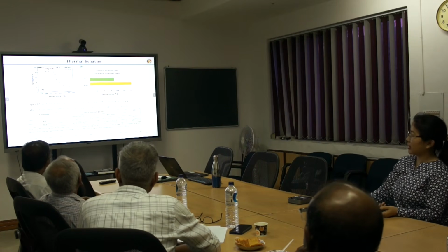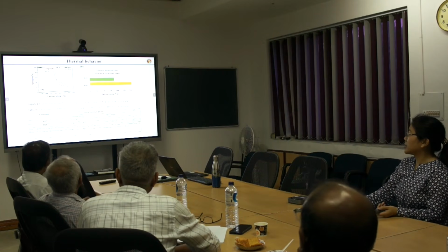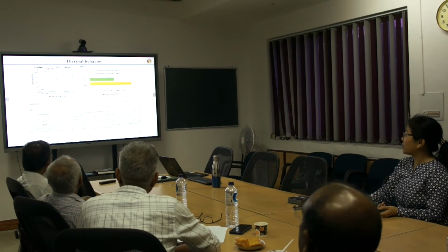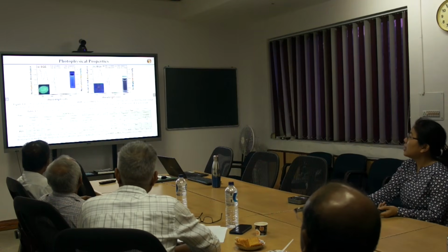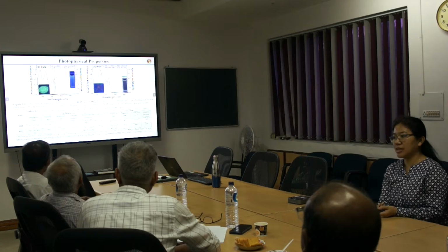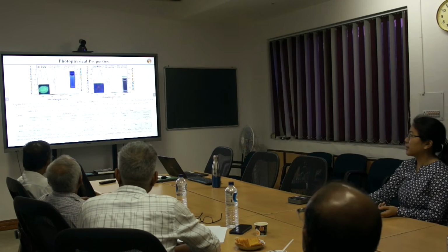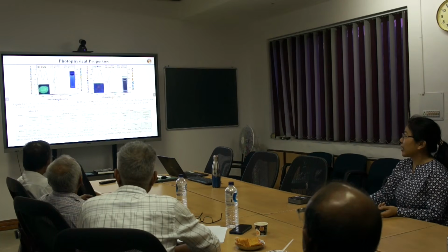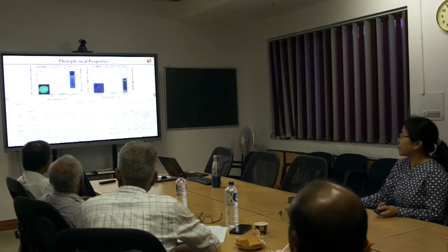And from thermogravimetric analysis, BQA, the amide compound, was shown to have 5% decomposition at 281 degrees, and for BQE it was at 345. And because of the difference in linkage of the derivatives, the BQE and BQA showed slightly different absorption and emission behavior.